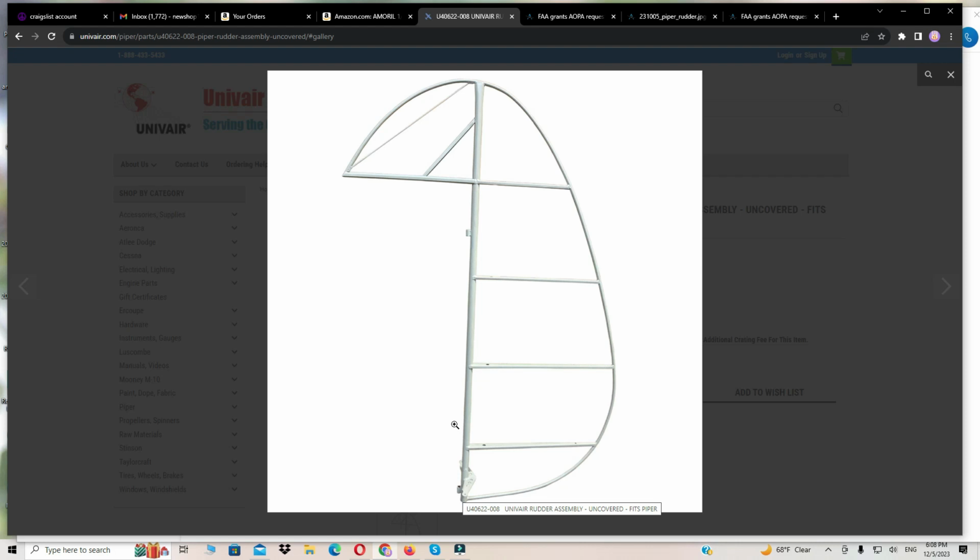Now, if we want to go the extra step, after we insert the carbon rod and the carbon fiber is already inside, we can make 2 holes, one here, one there, and put in bolts that will be countersunk from both sides, a male and a female, flush mounted with the rods, and do another 2 sets somewhere along this line. That makes sure that even if the epoxy for some weird reason decides not to stick, it will still hook up with those bolts, so it means that it will never turn. The top part of this rudder will never be able to torque and break itself out.